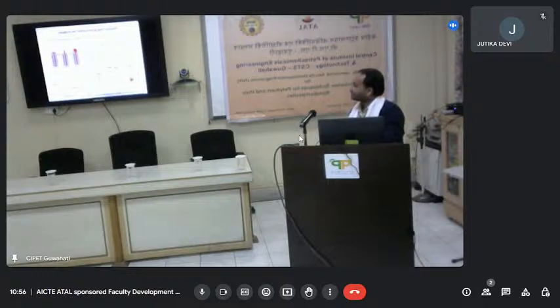These regions represent the ion saturation regions, whereas these regions represent the electron saturation regions. From the ion saturation region, using some formula, you can calculate the plasma density. That region is called the transition region. From the transition region, you can easily measure the plasma temperature.